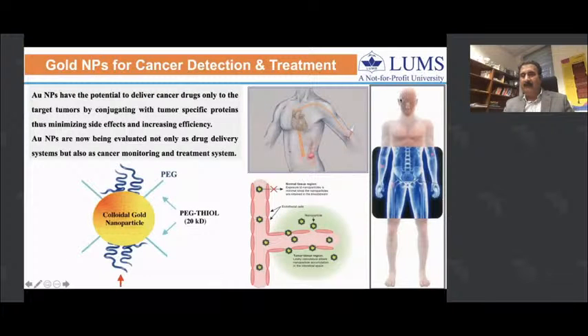So this cartoon, I believe many of you are aware of this. It is just a cartoon to show the potential of gold nanoparticles, which are 25 nanometer particles, to detect cancer at a very early stage and then simultaneously treat it as well. Once they are injected, they travel in the blood vessels, and the pore size of blood vessels is 5 to 10 nanometers, so they do not normally come out of this.